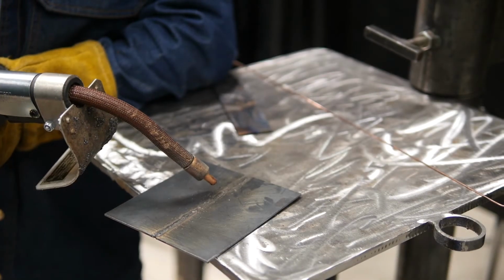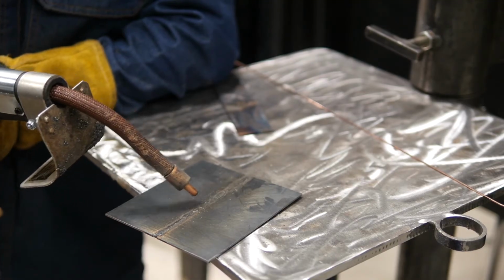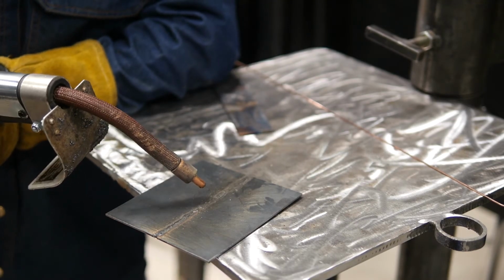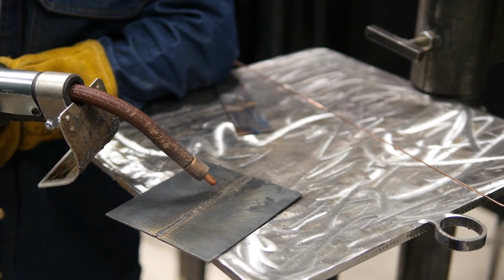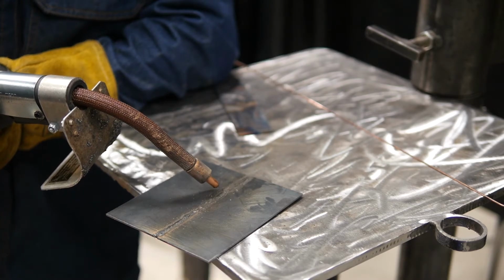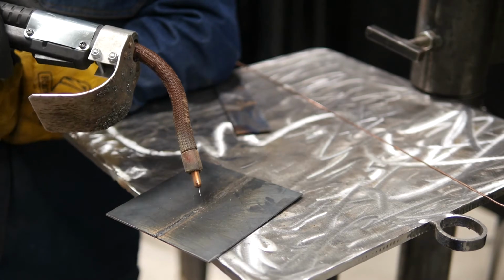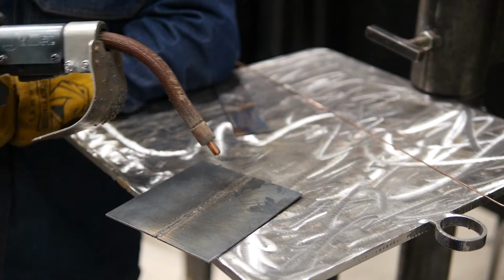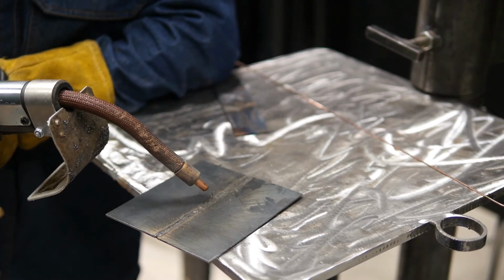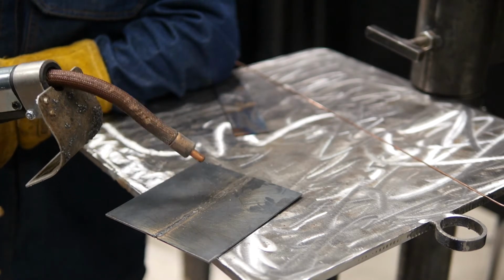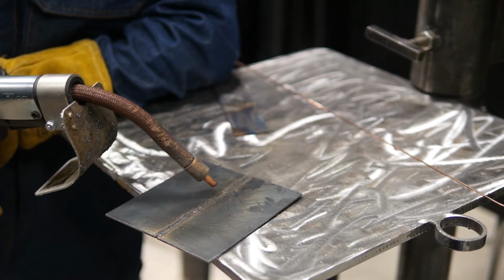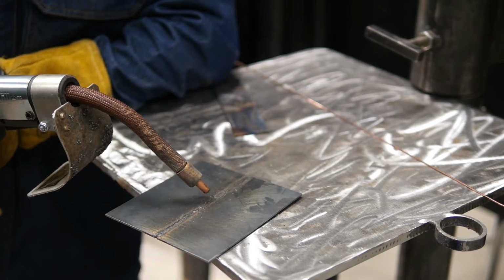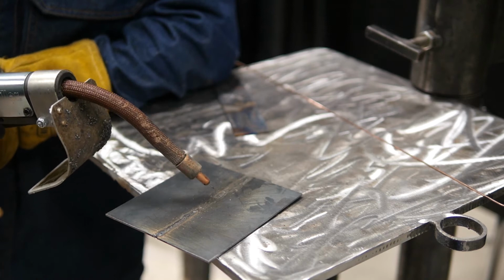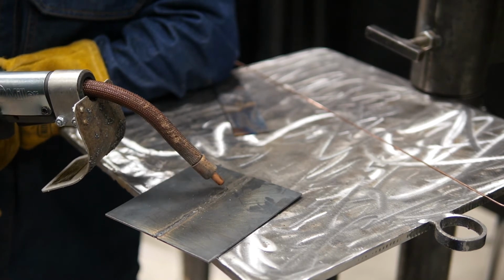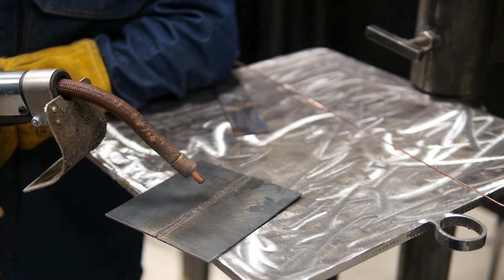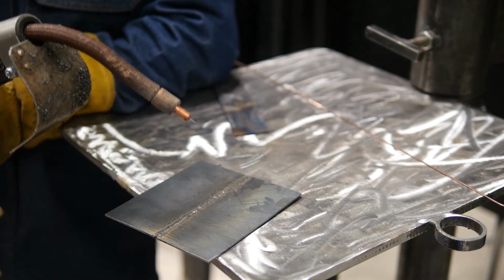There's a definite technique when welding with FluxCore, especially flat like this. And there's a saying, if there's slag, you drag. So if I'm right-handed, I'm moving from my left to my right. If I'm left-handed, I'm moving from my right to my left. This allows the slag that's produced from the flux inside our FluxCore wire to float to the surface and we can chip it off and it doesn't get stuck in our welds. Like over here, that little pinhole that we had was some of the slag that didn't quite eject itself out of the weld.